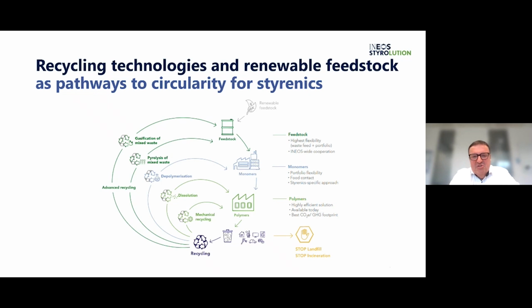If you go up even higher in temperature, so above 600 degrees, up to 800, 900, 1000 centigrade, you end up doing pyrolysis or gasification. And pyrolysis and gasification is important because you might want to use mixed waste, which otherwise cannot be separated, delaminated, used for mechanical recycling, or rather less preferential for depolymerization. Then pyrolysis and gasification cleaves the molecules into very small molecules that can be fed back into the chemical infrastructure which exists and can be reused for chemicals, for plastics, for example, but also other chemicals. So it's a way that makes use out of the otherwise difficult to recycle mixed plastics waste.